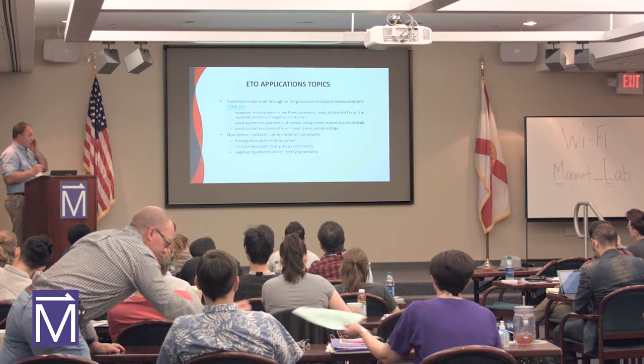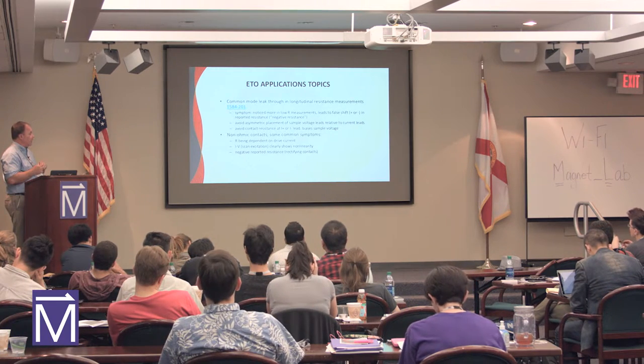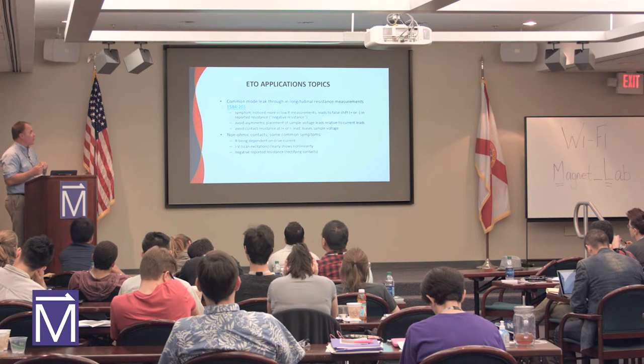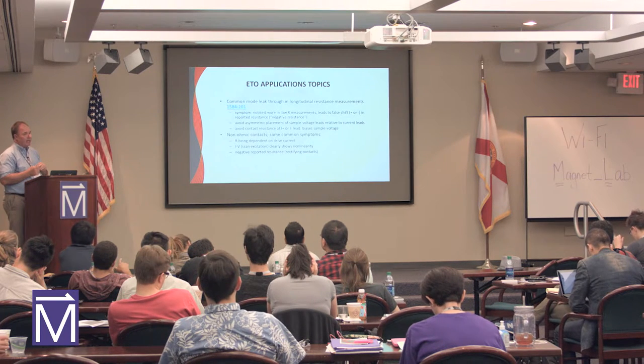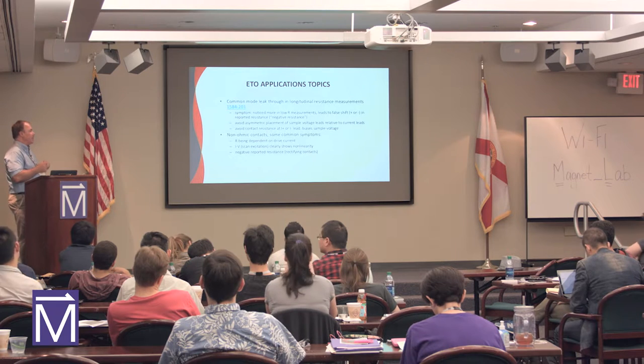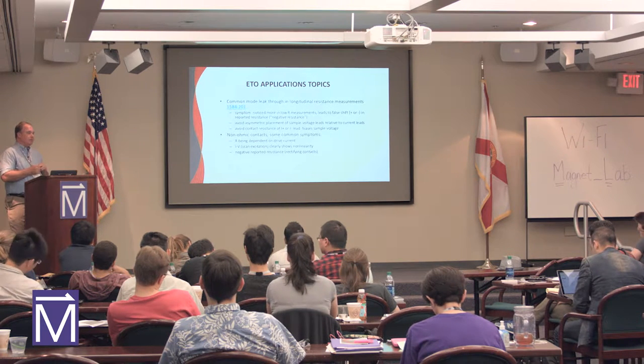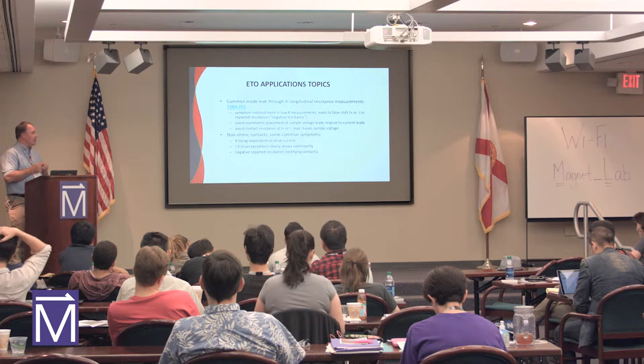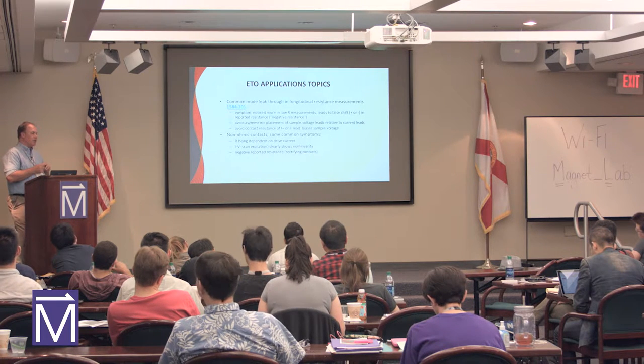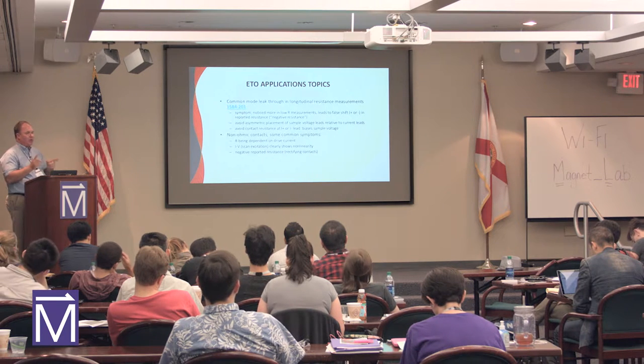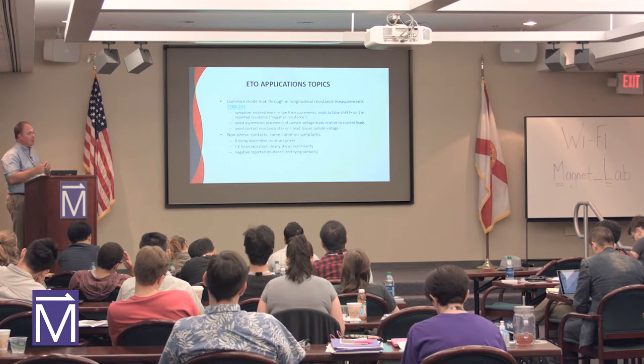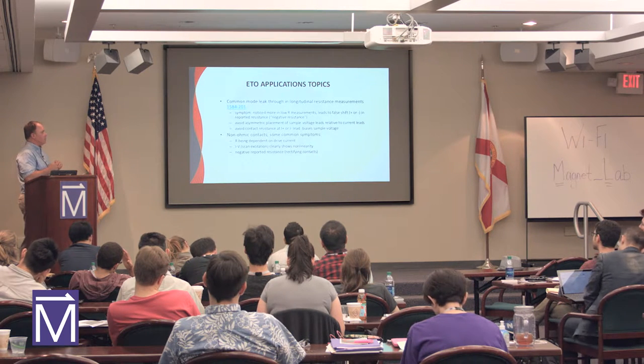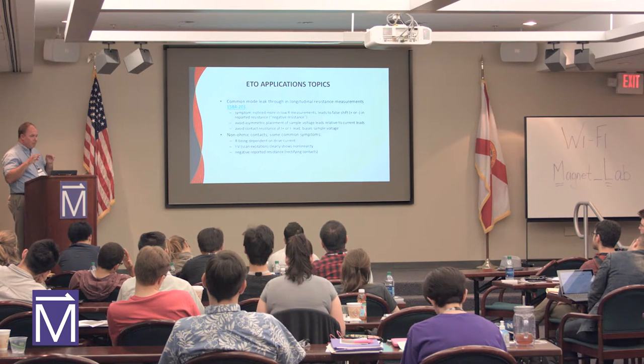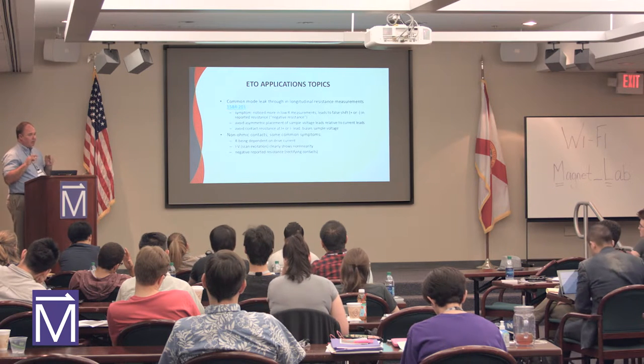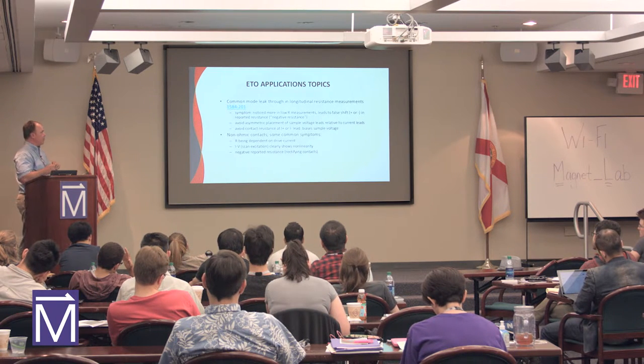We've got a couple of application notes that talk about common mode leak through. You may have a situation where you have this artifact in your measurement that reports a negative resistance of the sample. This application note describes this in detail. Essentially there's a couple of sources of this: where you put your connections on the sample, you might have a relative current, the way you wire bond or make your electrical connection to your sample.